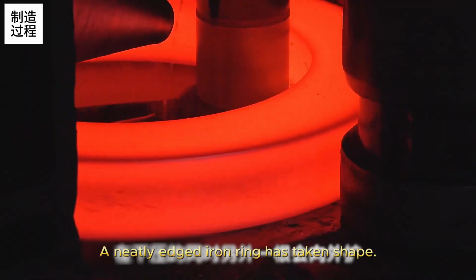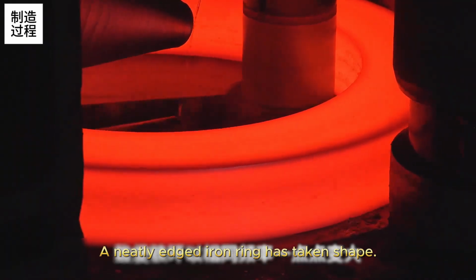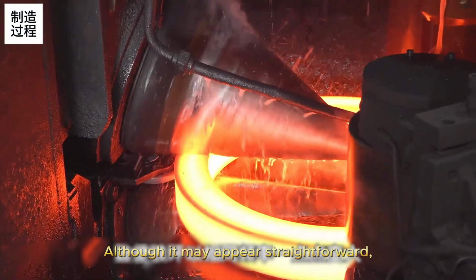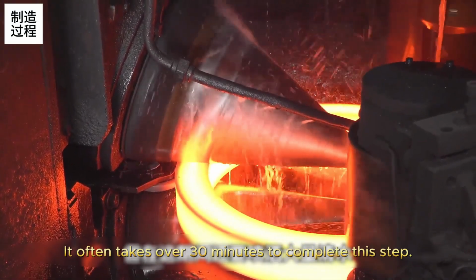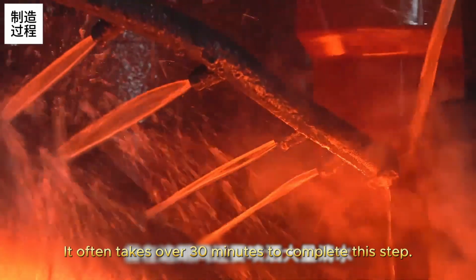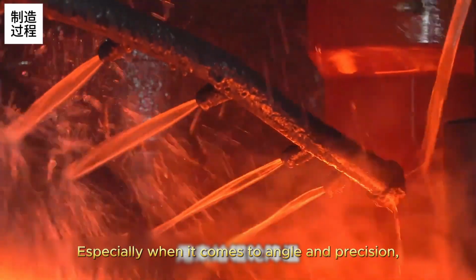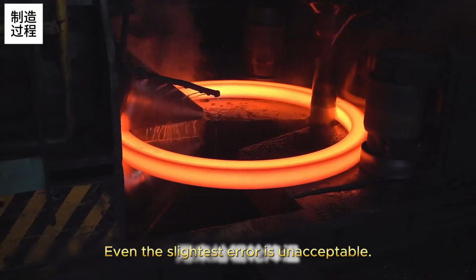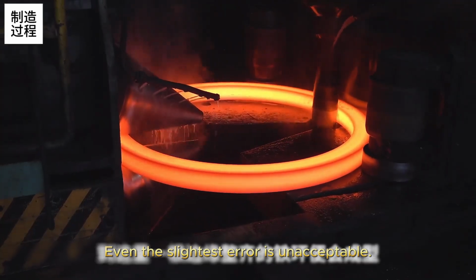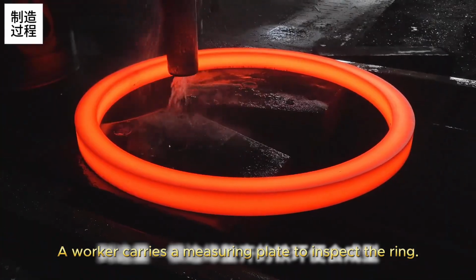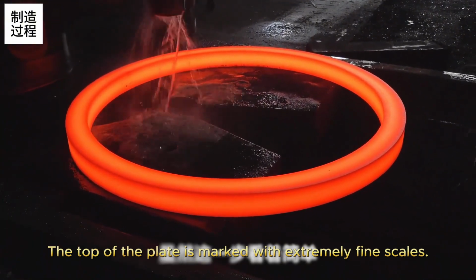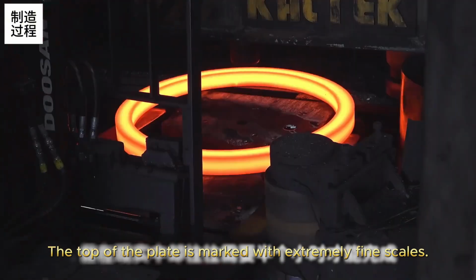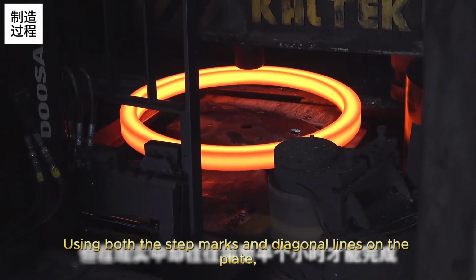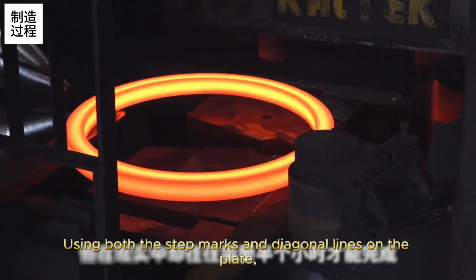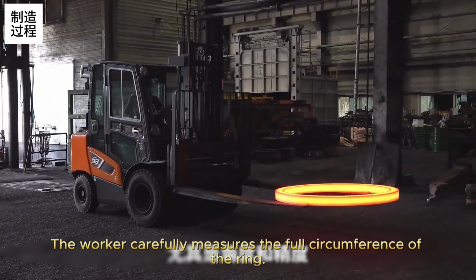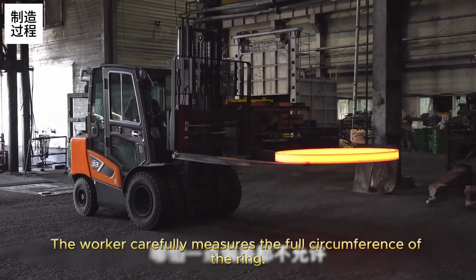At this point, a neatly edged iron ring has taken shape. Although it may appear straightforward, in reality, it often takes over 30 minutes to complete this step, especially when it comes to angle and precision. Even the slightest error is unacceptable. So, a worker carries a measuring plate to inspect the ring. The top of the plate is marked with extremely fine scales, using both the step marks and diagonal lines on the plate. The worker carefully measures the full circumference of the ring.